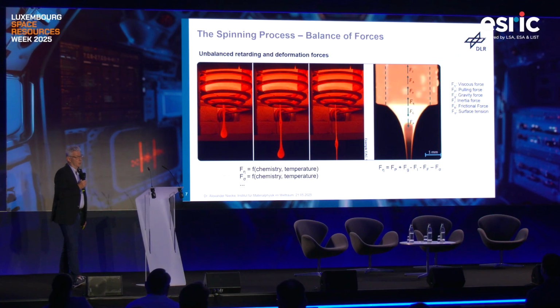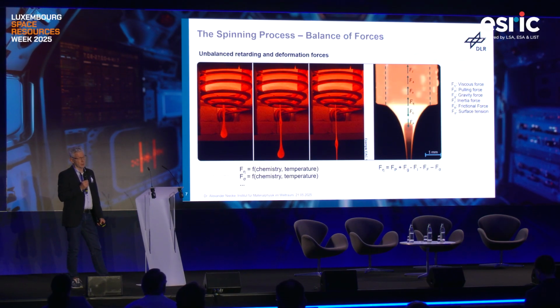In case this process is not balanced, that can happen. You see these imperfections in the glass jet that is extruded from the nozzle. These fluctuations of the size of this glass jet can be due to chemical variation, inconsistent chemistry due to the temperature.